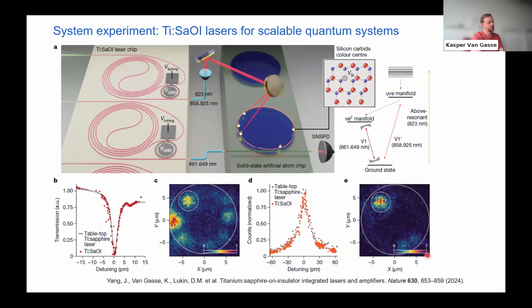And then finally, to just give an illustration, it's nice to say, oh, we're going to make titanium sapphire lasers on chip. It's good for quantum optics. But it's, of course, also interesting to really show that this is the case. So what we did is we made an array of these tunable titanium sapphire lasers on chip. And then we used them to control color centers in a silicon carbide optical resonator here. And what we did is perform this cavity QED experiment and actually compare the performance of a tabletop $500,000 titanium sapphire laser with our tiny on-chip tunable titanium sapphire lasers and really compare it 1-to-1.